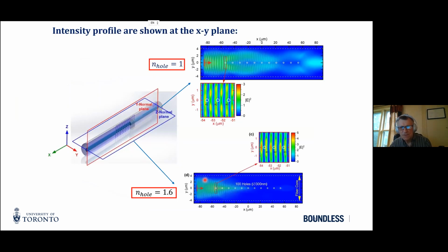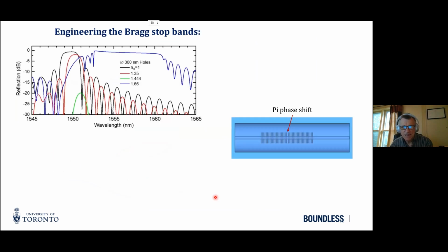What this allows us to do, these are just simulations of the optical field in the core, and you can get really strong stop band effects that really was not available in the fiber until this time. And so with very strong stop bands, you can make even shorter devices and play with, in this case, fiber Bragg gratings, but just high index contrast.